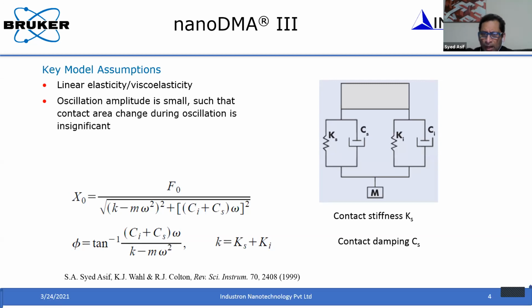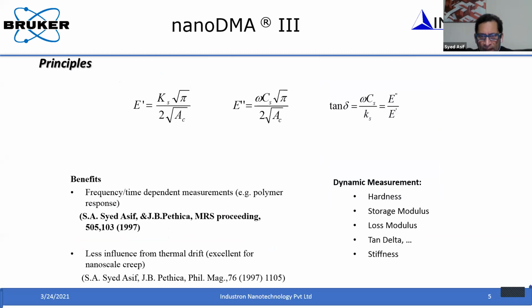The reason is, like Professor Prita Pant mentioned, that when you work in a quasi-static manner, depending upon the drift in the instrument, you will probably be measuring the drift of the instrument along with your actual measurement, and it is very difficult to deconvolute the actual measurement from the drift. But the drift is a low-frequency phenomenon, so if you do the experiment at a much higher frequency, you can avoid this drift problem and straightaway calculate the stiffness. Okay, so that is the basic difference between the quasi-static and dynamic techniques.